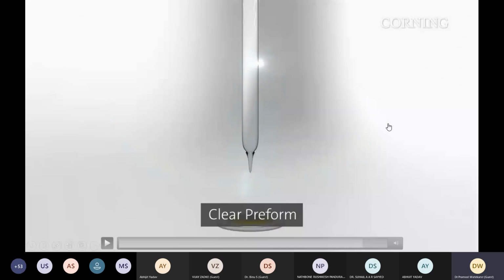Now we take this core rod, and over this, we deposit another SiO2 region, SiO2 layers, these particles. So another soot is formed, again put in the furnace, and we get the final structure, which is glass, which has now 2 layers. Inside there is core, outside there is SiO2.